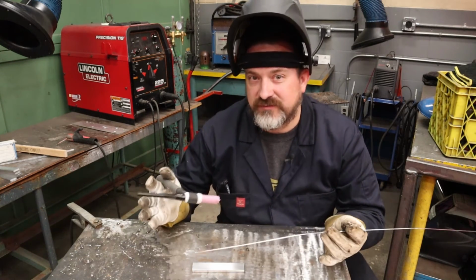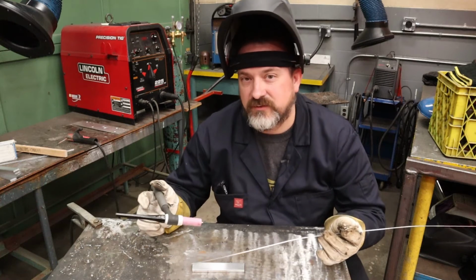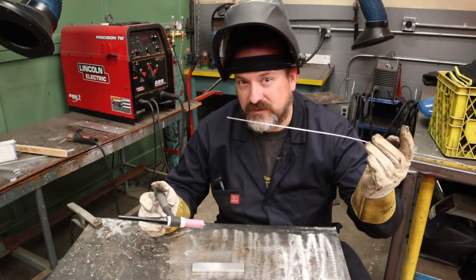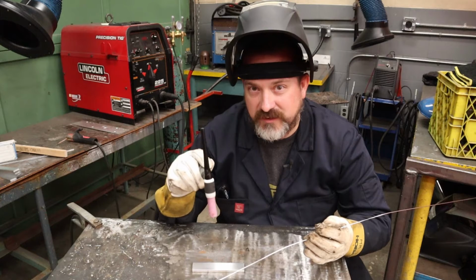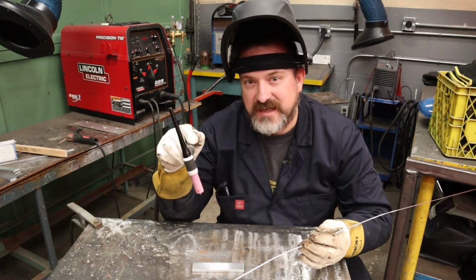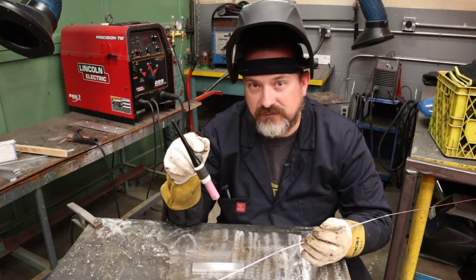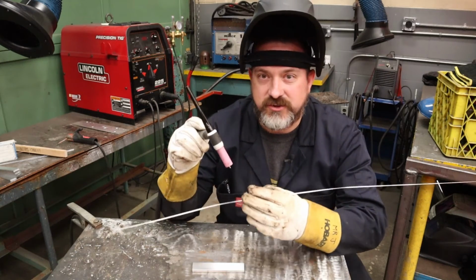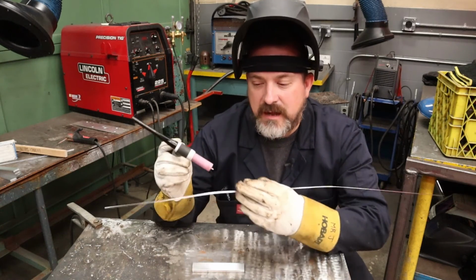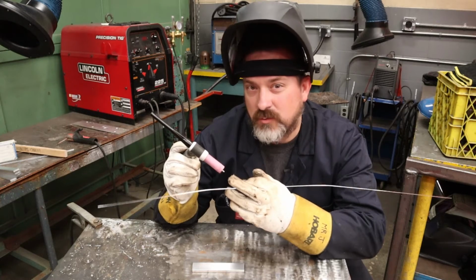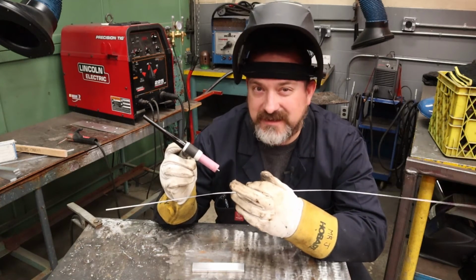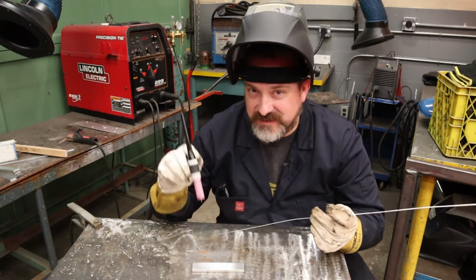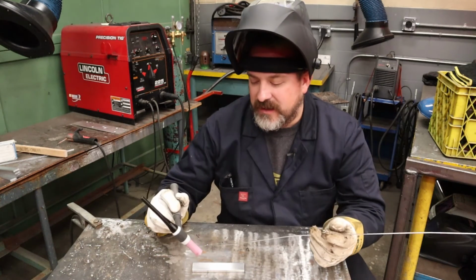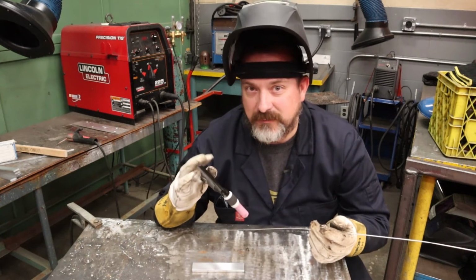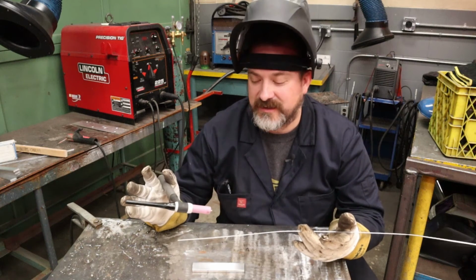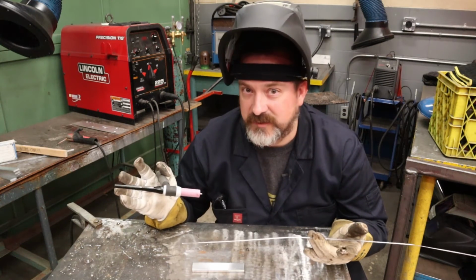Now, once you get moving, there's a whole bunch of stuff going on. You've got how fast you should be feeding your filler rod, how fast your torch should be going. There should be about a 10, maybe 15 degree forward angle of the torch. The electrode should be up off the material about the diameter of the electrode and no more than twice the diameter. So for me, it's about 1/8 of an inch without sticking and dipping it into the puddle. And you've also got your pedal control that you have to manage as well. So it's a lot going on, and this is why aluminum TIG welding can be tricky.